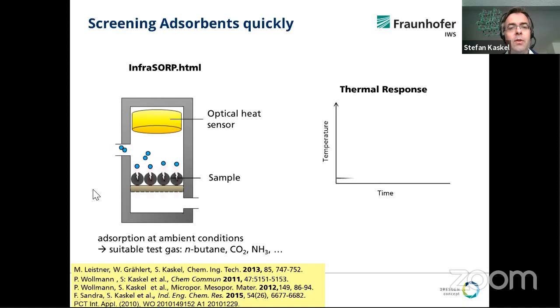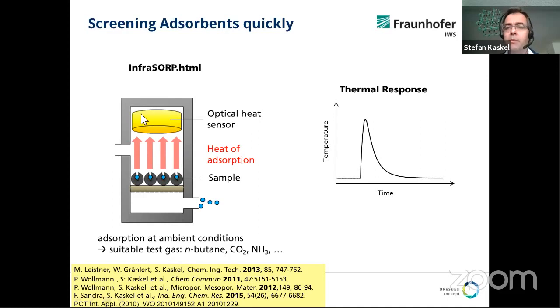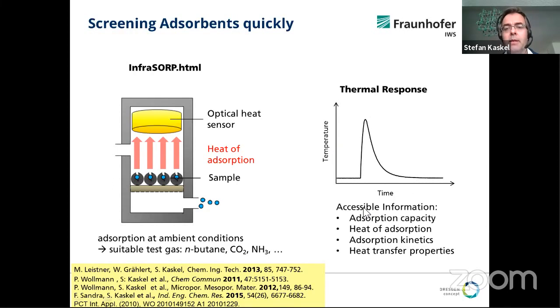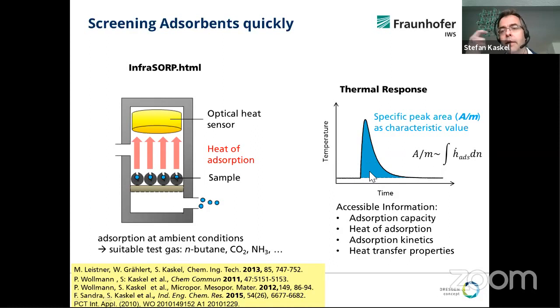And here you can use, for example, butane at room temperature, and you can measure the heat release not by a thermocouple, but by an optical sensor. This is an IR sensor, and this gives you basically a heat signal over the time. This is a continuous measurement, a flow measurement. So there's also cooling involved, and therefore the peak declines. But basically, similar as a chromatogram, the area under the curve basically gives you an indication how much gas is adsorbed, and you can derive information about the adsorption capacity, the heat of adsorption, but also you see how rapid the adsorption takes place. You can get information about adsorption kinetics, and in some cases even heat transfer.